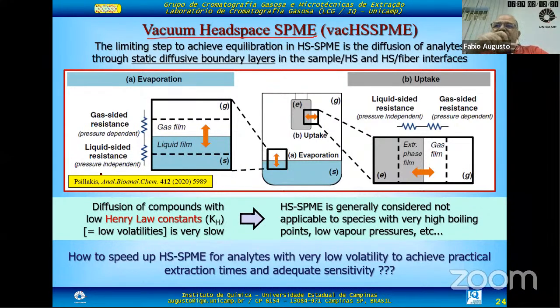Years ago, Professor Elia Psillakis at the Technical University of Crete started to ponder: the limiting step in headspace solid phase microextraction to reach equilibration is the diffusion of the analytes through the so-called static diffusion boundary layers that exist between the different phases in the system, between the liquid sample and the headspace, and between the headspace and the extracting phase on the fiber. They supposed that if you reduce the pressure and make some effort to accelerate this mass transfer, especially for compounds with very low volatilities, for example very low Henry's law constants, they could accelerate the overall process.